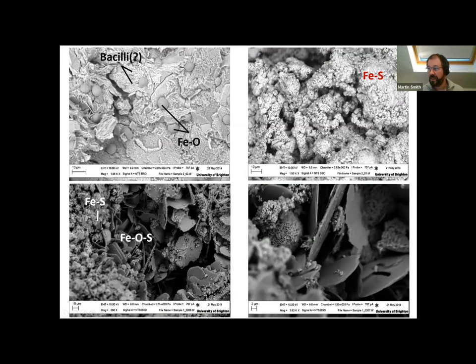So we see a laminated iron oxide material. It has a number of peculiar structures in it. These are either iron oxides or iron carbonates. In this case, we can actually see some bacilli on surfaces. If we look at the interior of those blisters, what we see is very fine-grained, microcrystalline to amorphous iron sulfides, probably mackinawite, alongside well-crystalline green rusts, iron sulfate phases. And you can see that in very high magnification here, platy green rust minerals alongside acicular iron oxides of various sorts.